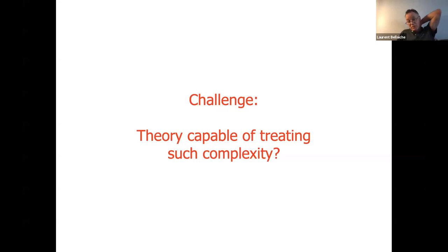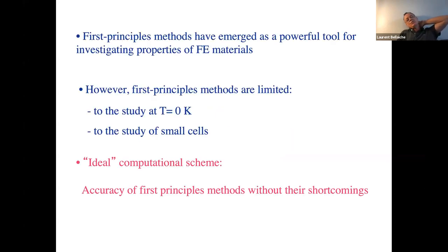Is it possible to develop or use a theory that can treat such complexity? Since the 1990s, first principles methods have been used in perovskites and ferroelectrics, and have been very, very useful. In my mind, it's a huge revolution to have used these DFT calculations to understand these systems. But most of the time, they are limited by two big limitations. Most of the time, you stay at 0 K, even if these days you can do finite temperature effects in DFT. And a big problem in my mind is that you study small cells, in the sense that 200, 300 atoms is already a big deal with DFT.